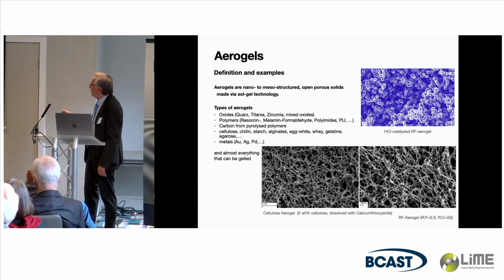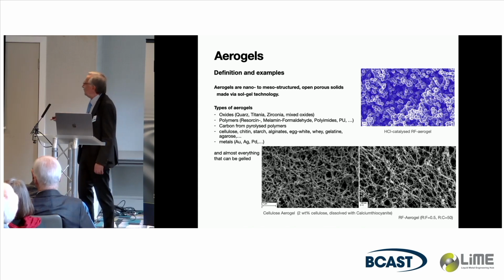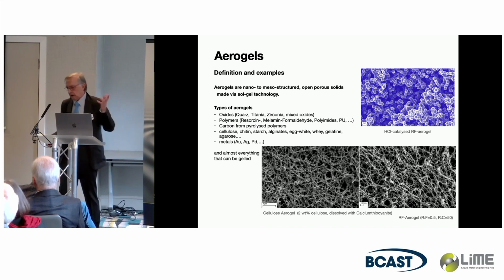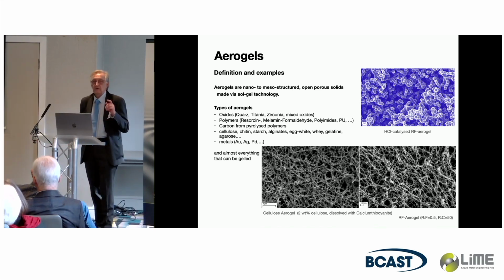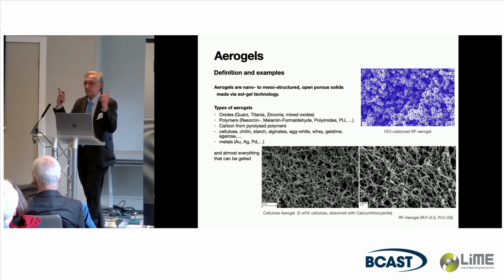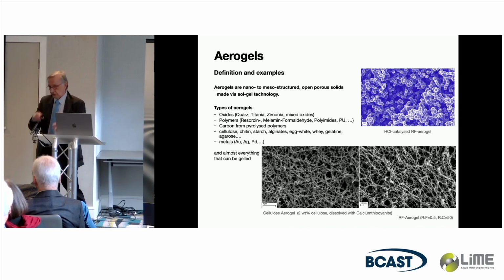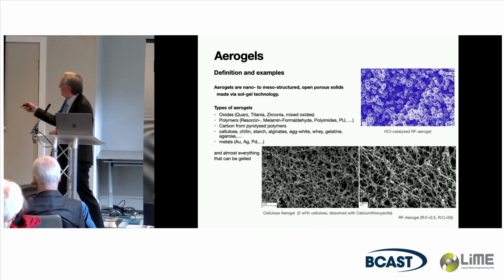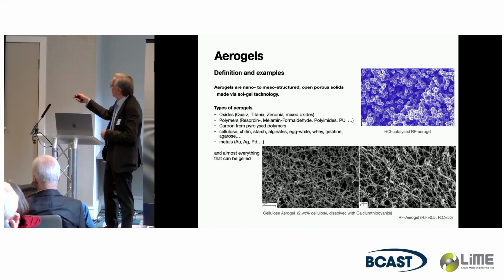You can use biopolymers, cellulose, gelatin, egg white, agarose, and recently, 5 to 10 years ago, Eychmüller in Dresden made a lot of metallic aerogels out of almost all metals. You just need to have a metal salt, and you can transform this into an aerogel. So, open porous structures like this here.